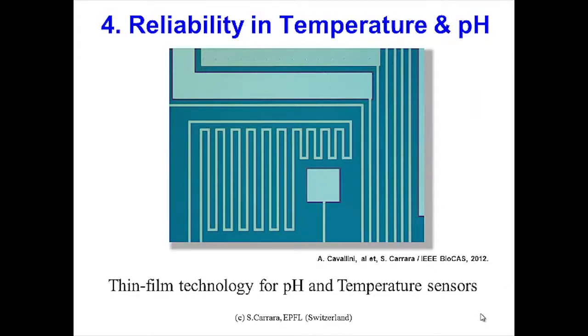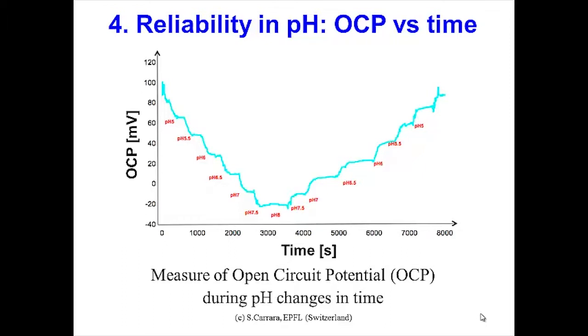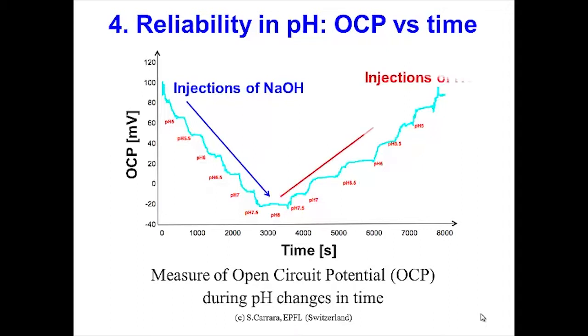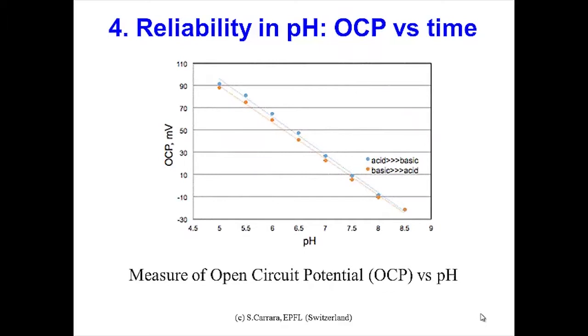We integrated with the thin film technology just a platinum resistor on the platform to realize the temperature sensor. We also realized a junction facing platinum and iridium dioxide in order to obtain a pH sensor, because this junction is very sensitive to the pH. This is just one experiment in which we acquired the open circuit potential, injecting NaOH into the solution in order to move from low to high pH, and then we injected hydrochloric acid again in order to move from high pH to low pH. As you can see, the sensor registered all this variation quite well, and in the calibration curve we see that they are extremely linear, both moving from acid to basic and from basic to acid.